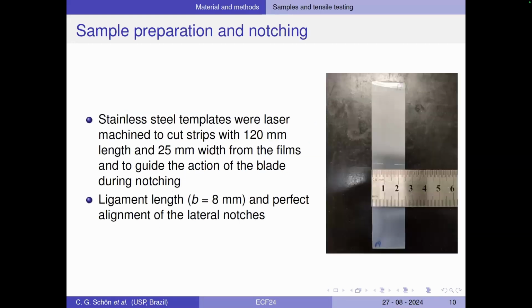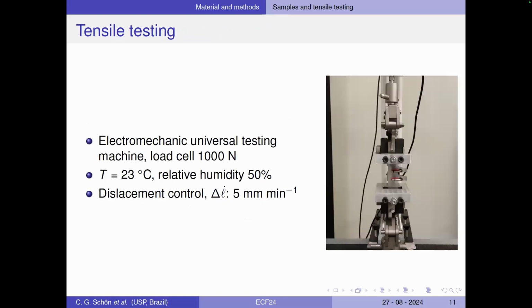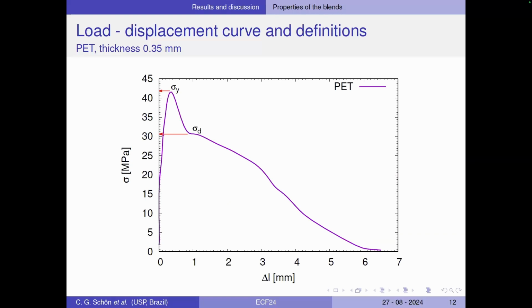The kind of sample we did is a double edge notched tensile test, simply because I wanted to do EWF, and they didn't want to do EWF. So they skipped it with 8 mm ligament length. They constructed a device to perform the test. And of course, this is the load displacement curve of a DENT test, and to define the two quantities we are reporting here. And of course, also the integral of the curve is the work of fracture, which is specific if we divide by the ligament area.